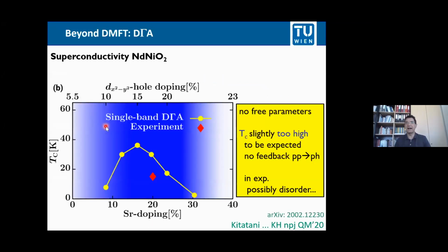We can then calculate the phase diagram, critical temperature versus strontium doping. As I explained before, we have to carefully use our fully multi-orbital calculations to translate the strontium doping to a doping of this single x squared minus y squared orbital. So it's this 5% for the undoped compound, and then you end up with something like 17% for 20% doping. And that is our result here. That is our TC. And at the time, in February last year, we calculated this phase diagram. There was only one experimental data point for this 20% strontium doping.